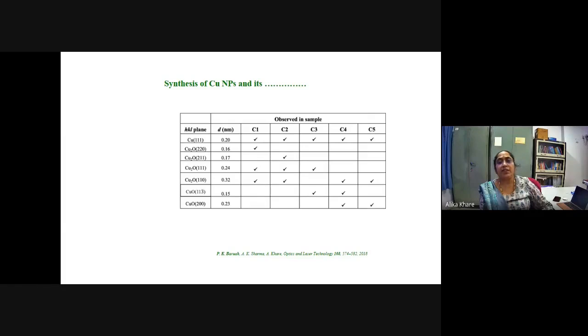C1, C2, C3 is changing the time with fixed laser energy, and C3 to C5 is fixed time with increasing energy, time meaning exposure time of the laser. One can see that we are able to get less oxidation under certain conditions and higher oxidation under other conditions. Therefore the properties of the nanoparticles can be very well controlled by controlling the laser parameters and exposure time.